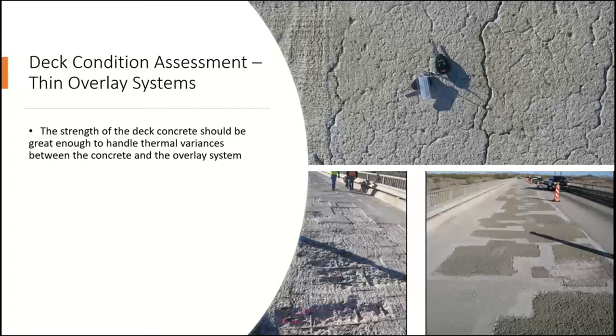It's not a problem if the deck has good tensile strength and you don't have a lot of patching. We'll talk a little more about condition assessment, but it's real important. So if you look at this picture here, I was on this bridge, and I was on most of the bridges where many of these photos were taken. If you look at the bottom left, what happened is a Bobcat-mounted milling machine came out there, which created a lot of vibration, probably a lot of micro cracking during the process, especially when it came in contact with the reinforcing steel. And as we would drag a chain around on this deck, the patching kept expanding and expanding and expanding.